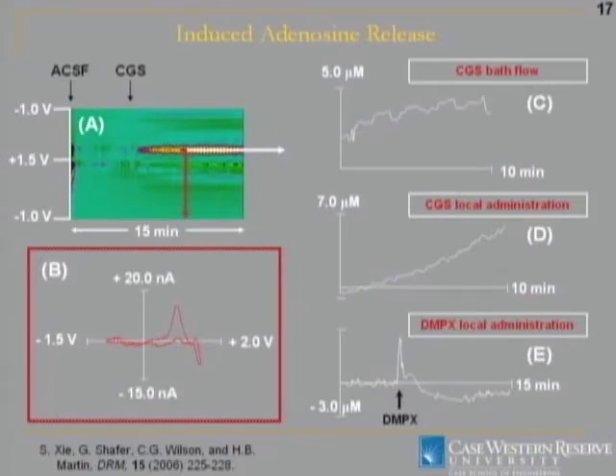We did several experiments. Here's actually the voltammogram showing the oxidation peak for adenosine. And we did several different types of experiments to try to verify we were seeing adenosine in the tissue, bath administration versus local administration of the agonist. We also put a blocker in and saw the concentration go down. So we were relatively confident that we were seeing adenosine.